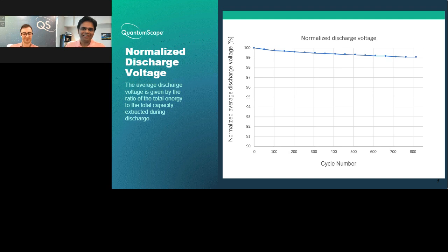where there was a class of high nickel cathodes where the capacity was not fading at all, but the voltage was fading. And so eventually, from a customer's perspective, you need both capacity to not fade and the voltage to not fade. So if either one of them fail, then the overall energy delivered is much lower. That means lower range for your EV. And so it's very important that both don't fade. Of course, the first graph shows you that the product of those two are not fading. And this shows additional data that supports the fact that the voltage is not fading.